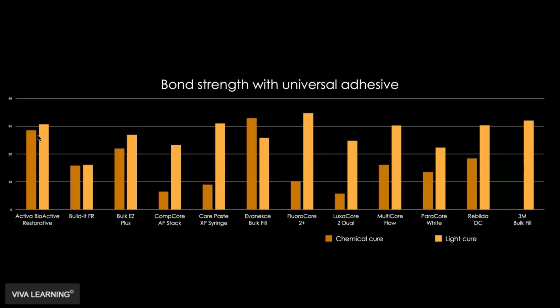There's a couple of materials that have the dark bars. These dark bars are good, meaning that they can be compatible with something like Scotch Bond Universal, even if you don't light cure them. So that's where Activa does really well. There's another one called Evanesce Bulk Fill, which is another dual cure bulk fill material, but the Activa is a dual cure bulk fill material that seems to be compatible with universal adhesive like Scotch Bond. So that's good.